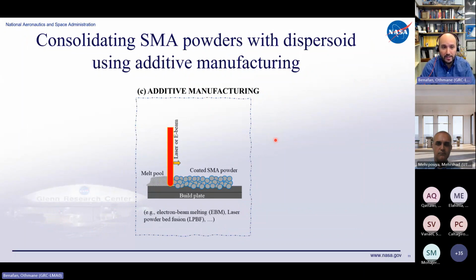I don't have to introduce additive manufacturing to this group, but in this particular one, we use laser powder bed fusion, and you're familiar with how that goes. So we just apply the powder that is pre-coated, and we apply our laser parameters: feed rate, hatch spacing, scanning speed, etc., environments, and all those good things that we all use in laser powder bed fusion. But it's not limited to that. You can use E-beam or other types of additive manufacturing as well.